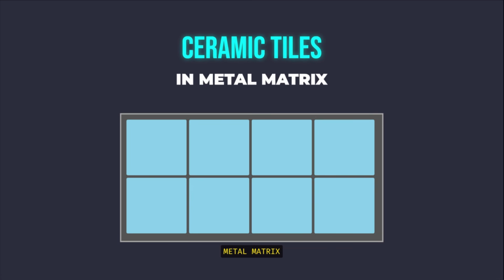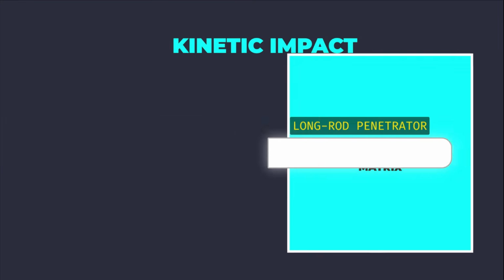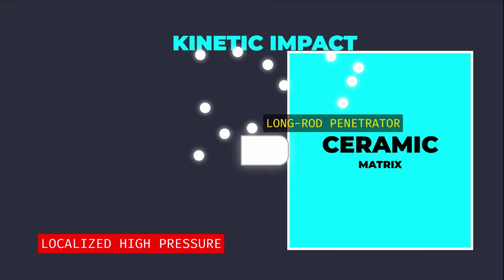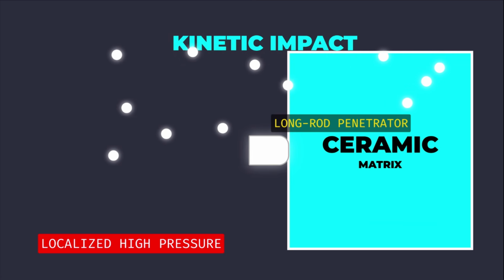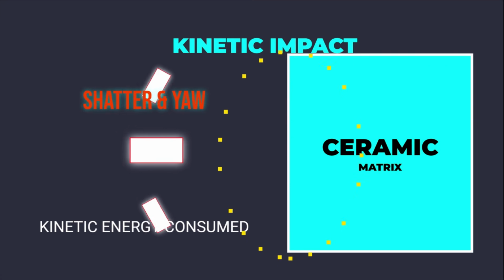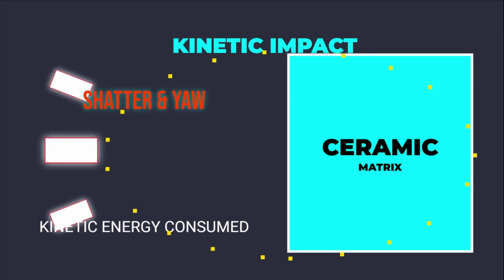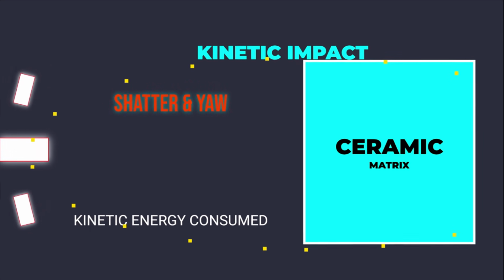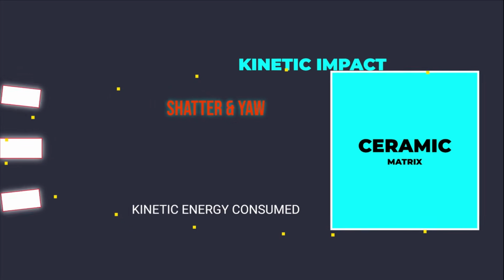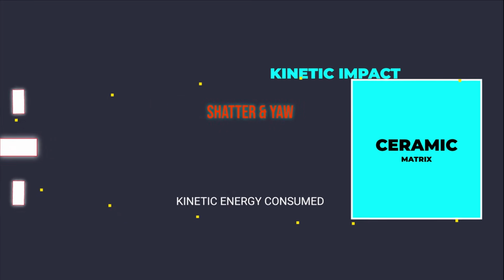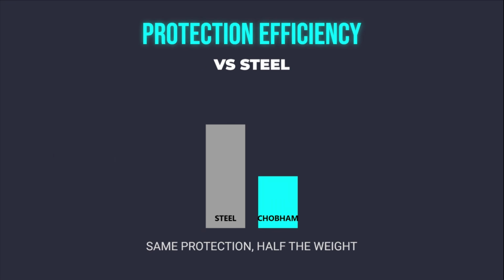Its core innovation lies in using extremely hard, brittle ceramic tiles encased within a metal matrix. When a long rod penetrator strikes the ceramic layer, the localized high pressure causes the ceramic to fracture into a fine powder. This process consumes significant kinetic energy and, crucially, causes the incoming projectile itself to shatter, yaw, or erode rapidly, preventing deep penetration into the hull. This mechanism provides superior protection against high-velocity, armor-piercing, fin-stabilized discarding sabot rounds compared to equivalent-weight steel armor.